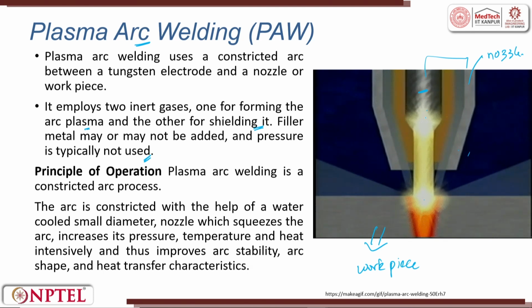If necessary, you can add a filler. Here you can see the arc is created and then the heat is generated. In the heat zone you can keep a filler, otherwise you can melt the material and then join. Principle of operation: plasma arc welding is a constricted arc process. The arc is constricted with the help of a water cooled small diameter nozzle, which squeezes the arc, increases its pressure, temperature and heat intensity, and thus improves arc stability, arc shape and heat transfer characteristics. Arc stability is improved compared to TIG, MIG and submerged arc welding. Arc stability is very high, arc shape is good and heat transfer is highly efficient.